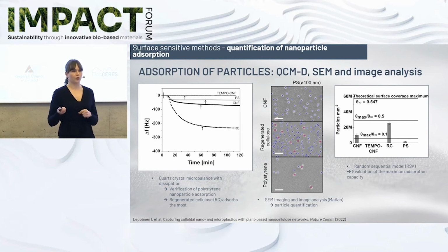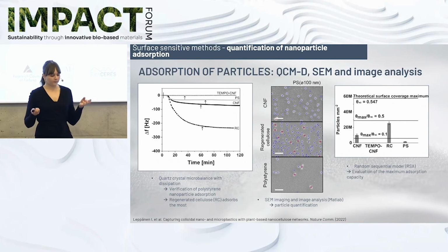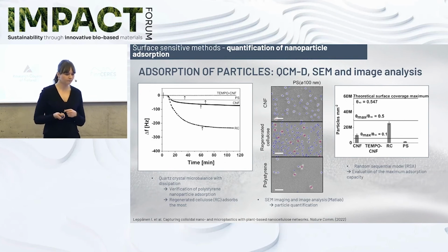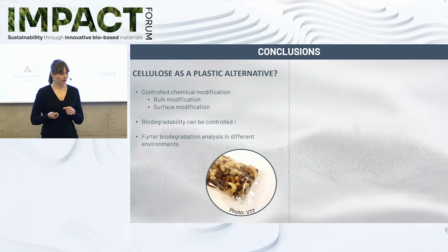So this really shows and validates that regenerated cellulose is very efficient in capturing the nanoplastic particles, and also kind of proves that it could really be used as a surface in analyzing and capturing the microplastics. So then to the conclusion.